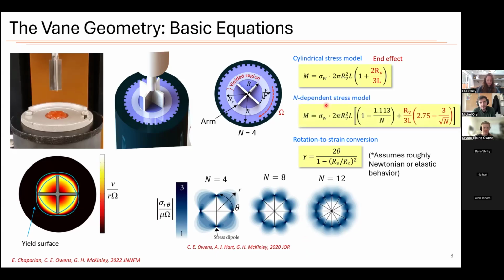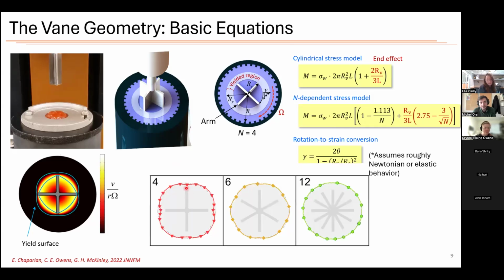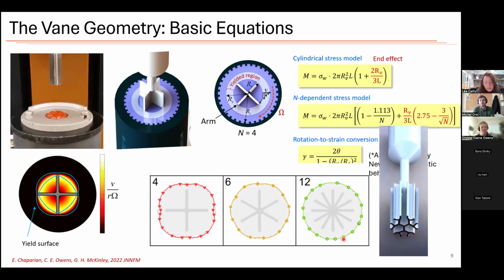And so we introduce a second stress model that takes into account the number of arms. It's a little bit more accurate than something that just assumes everything is a cylinder. We did more studies to see what is the yield surface for vanes with different numbers of arms. And we found that once you get to about 12, it's pretty much circular, like that becomes a decent approximation. And so for our studies of ketchup, we are using a 12-arm vane.